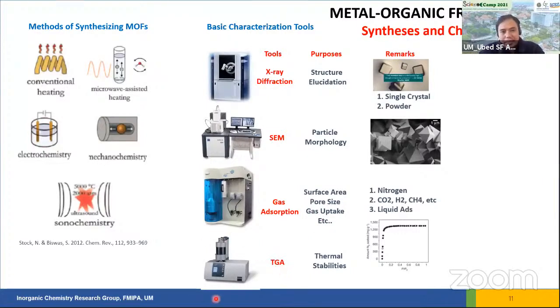The last one is thermogravimetric analysis. This tool is used for thermal stability examination. As we already know, MOF contains organic ligands, and organic ligands are not really stable at high temperature. So we need to examine their thermal stability. Usually metal organic frameworks are stable up to 300 to 450 degrees Celsius. So we use TGA to examine the thermal stability.